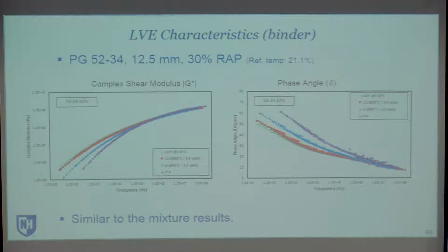Again, the same mixture, seeing the same kind of trends that we saw with the mixture testing, where the viscoelastic response of the 12-day and the 24 aging conditions are statistically similar. That 5 days is kind of at that midpoint. And we're seeing the same thing in the stiffness as well as the phase angle.